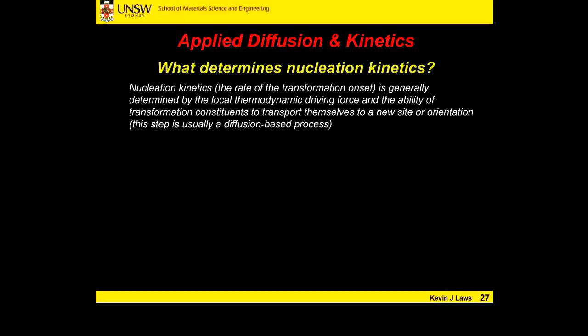So local thermodynamic driving force: there has to be something going on in a specific location where our reaction is taking place for nucleation, for that reaction to start. It could be something on a surface, right? You might have an impurity on a surface. You might have an impurity in your alloy melt or your chemical melt. And that impurity locally provides a site of lower activation energy for that reaction to start. Right? It could be the edges of your beaker, something like that.